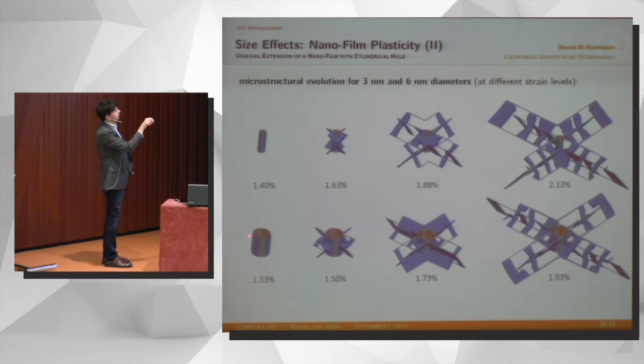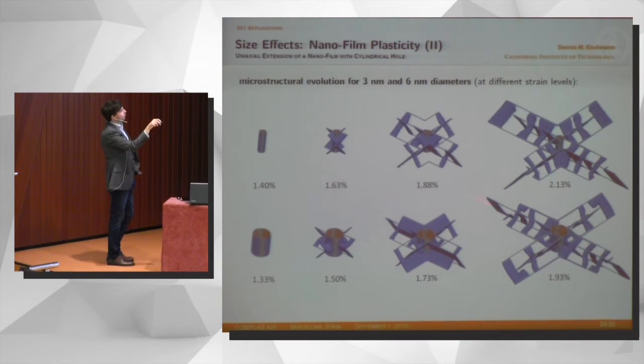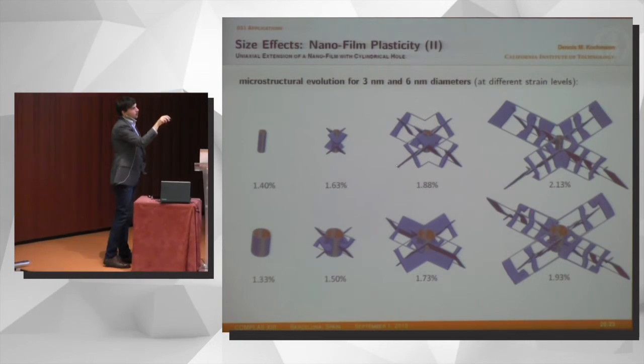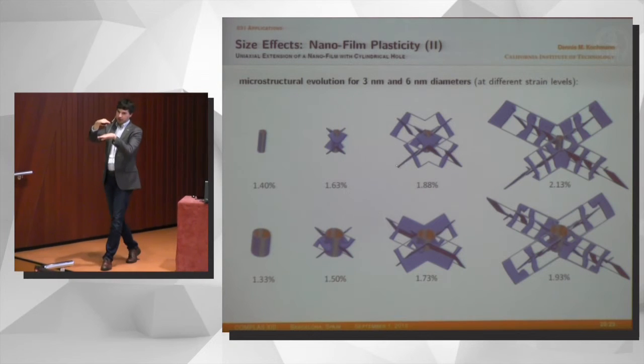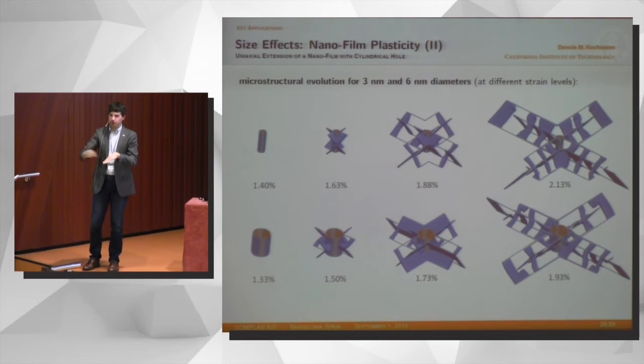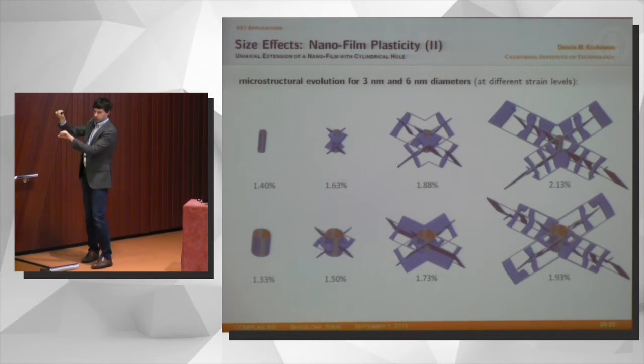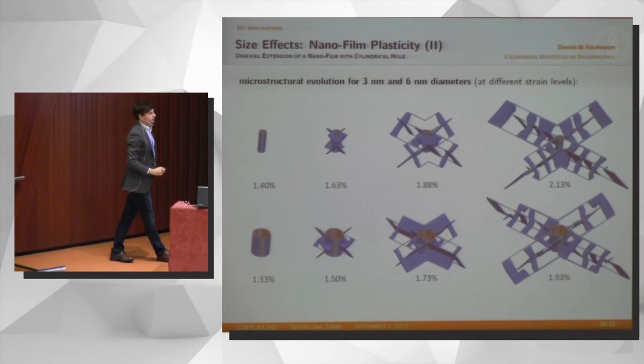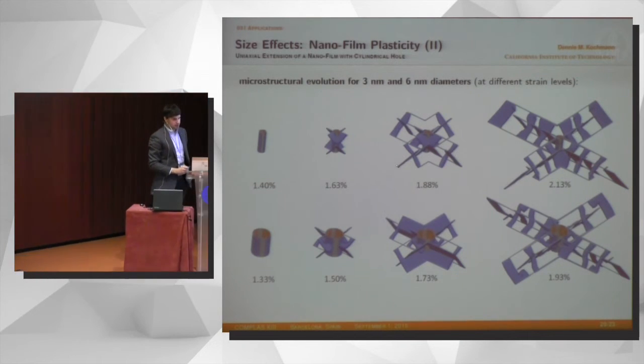We start with the hole. This is color-coded by centrosymmetry. Then you can see the loops running away from the hole, for the smaller one happening later than for the bigger one. And they look a little funny, but that's only because you have a thin plate. So you don't see perfect loops, but these loops have to end on the surface, and they're pinned. And that's why you see these intricate dislocation structures appear.